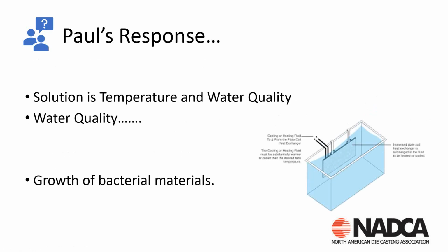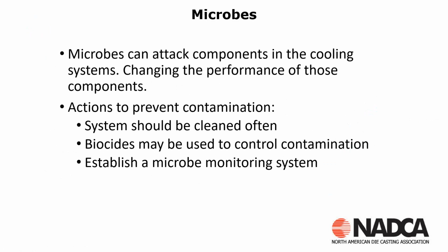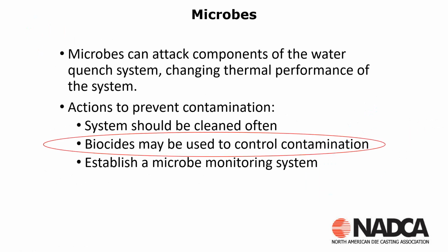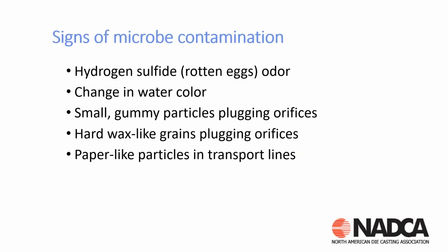So we have temperature, and then we have water quality. And that's frankly going to be growth of bacterial materials inside the quench system. And that's what was mentioned here. So we've got microbes that are going to attack the cooling components, changing the performance of those components. Action to prevent that kind of contamination is going to be some sort of biocide or a quench solution that can be added. There are several commercial quench solutions, and if you want, you can email me and I can get you some names of those solutions to be added to the quench system that will then overall clean and keep that biological contaminant down.